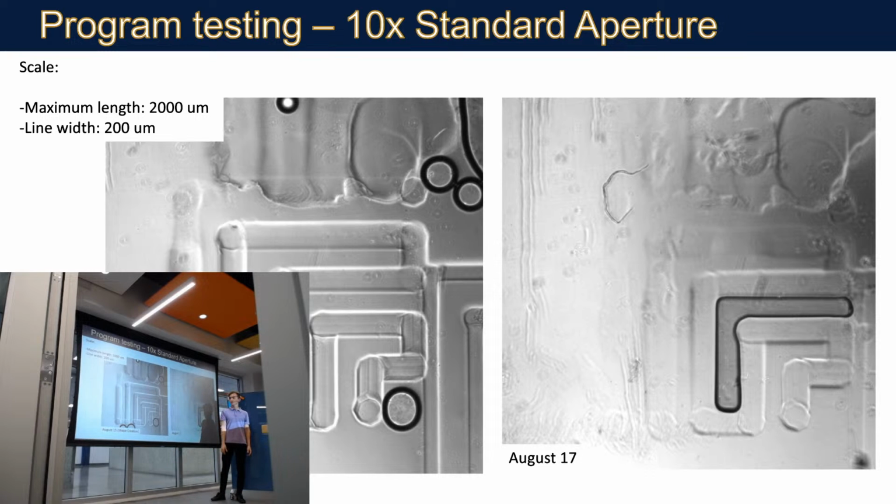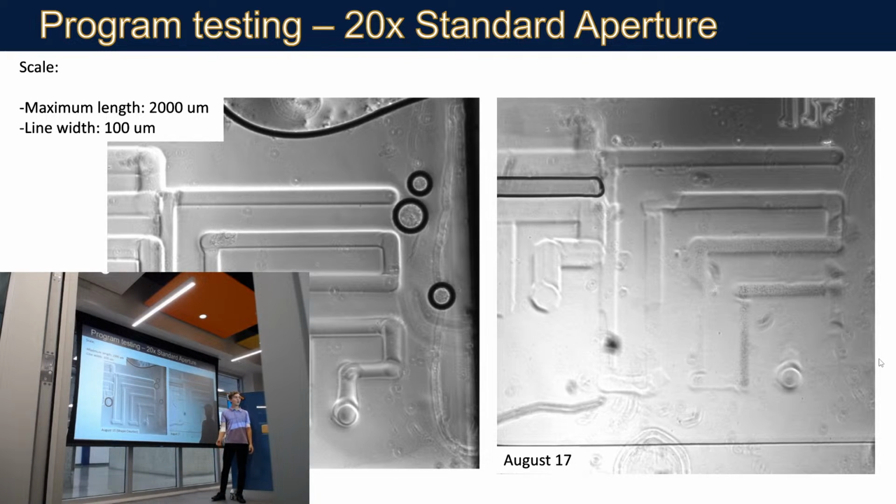And next one. We were testing how well it solidified. And you guys can see that this was August 15. Then after 2 days, it looks blurry because apparently what happened was that it solidifies from the bottom. Lighting is on the bottom. So it is like not getting solidified on the top. So after 2 days, we were able to see, by flowing liquid, that this part on the top wasn't solidified, as well as it's seen here.